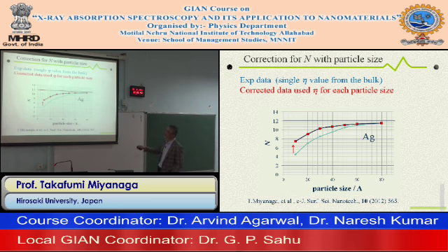The green one is from direct curve fitting using the single-atom data from the bulk, using FEFF or Artemis. And now we correct it by taking into account the nanoparticle effect via plasmon excitations. The correction data is higher, not so small.